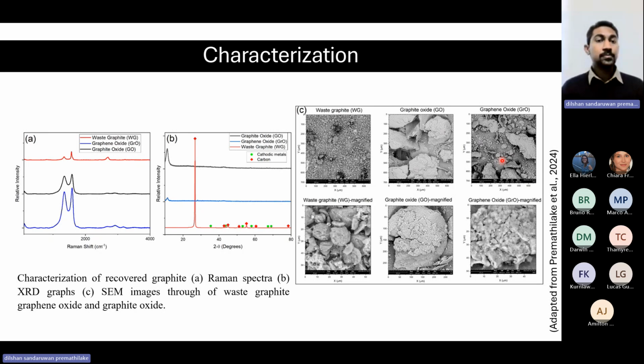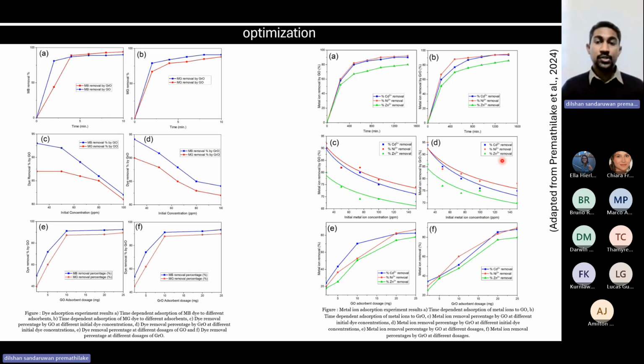Here, I tried to optimize the adsorption of dye and also the adsorption of metal ions onto these two different adsorption materials that I produced from the waste graphite derived from lithium-ion batteries. In the first one, you can see how I did the optimization of the adsorption time, the initial concentration of the dye, and finally the adsorbent dosage that I have to use. I did the same thing for the metal ions as well.